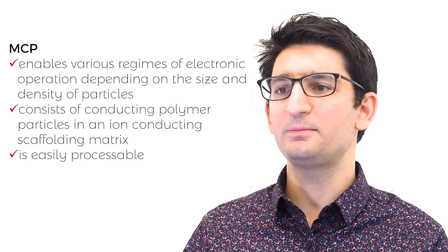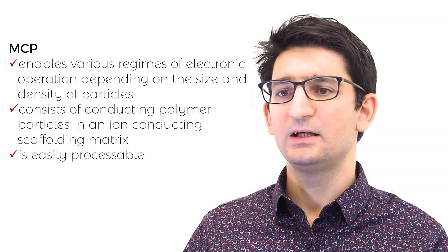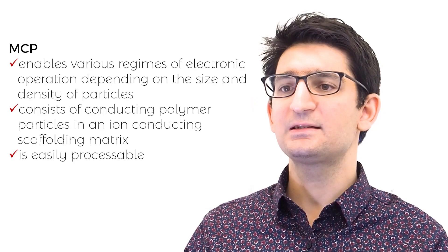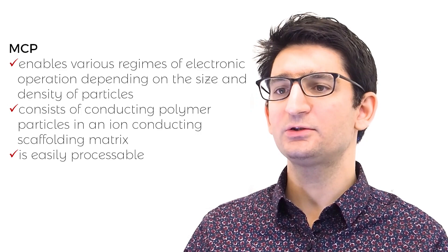We demonstrate that the combination of MCP with simply patterned electrical terminals can be used to create functional isotropic films, independently addressable transistors, resistors, and diodes. The composite nature of MCP endows it with multifunctional properties that can provide simplified device architecture that previously required multiple layers and interfaces, such as transistors and diodes.